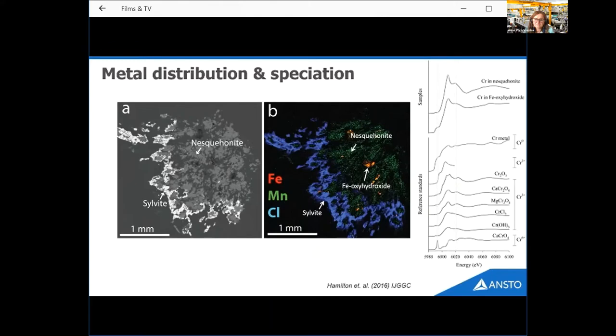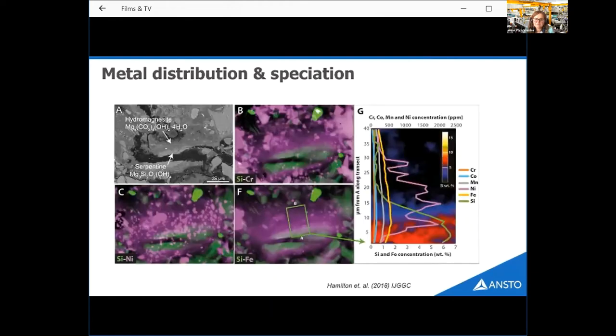That was all well for a synthetic system, but the next question is, okay, what happens in an accelerated natural system? So we then looked at mine tailings that had been carbonating for 30 years and had built up this carbonate cemented crust over the top. We mapped elemental distributions in those crusts, and in particular, we were looking across grain boundaries between the reactive grains and the carbonate cements forming on them. We saw again that all the transition metals we looked at were strongly retained in the carbonate cements.